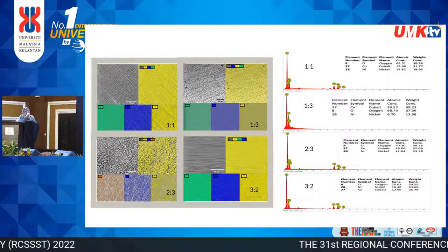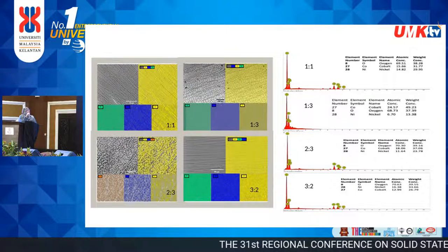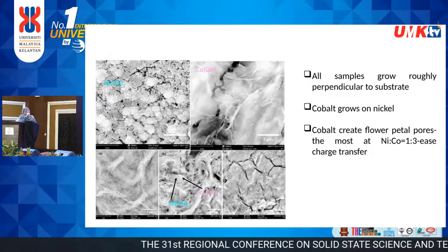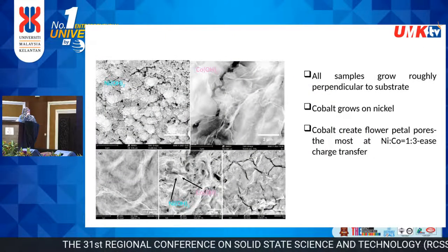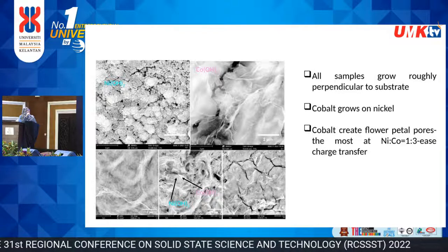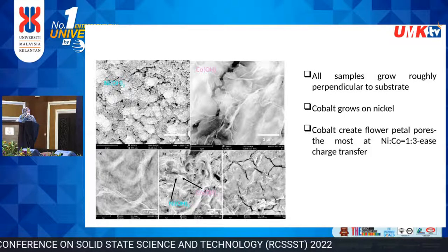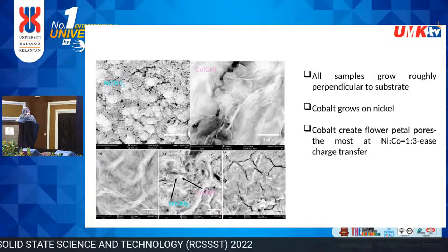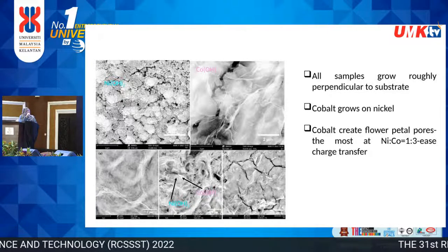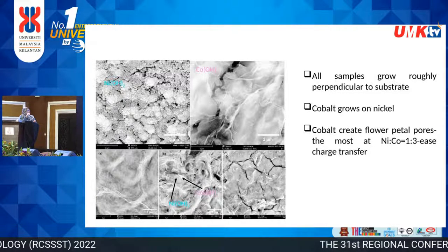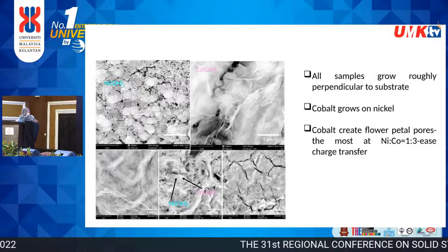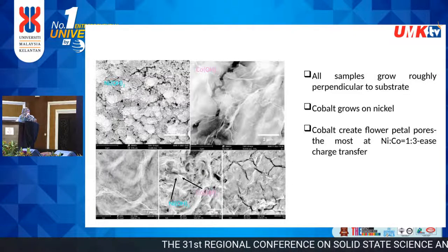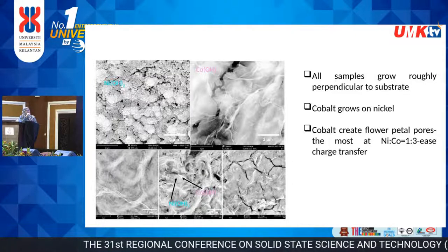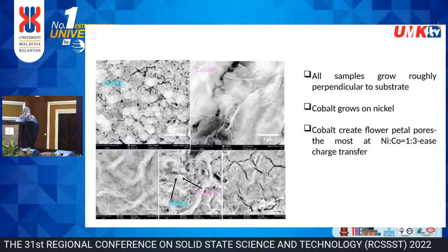Okay, this is the same image of the nickel cobalt hydroxide. You can see that all samples grow roughly perpendicular to the substrate, and cobalt grows on nickel. Cobalt actually creates pores, like flower-like pores, at nickel cobalt 1-3. These pores ease charge transfer.